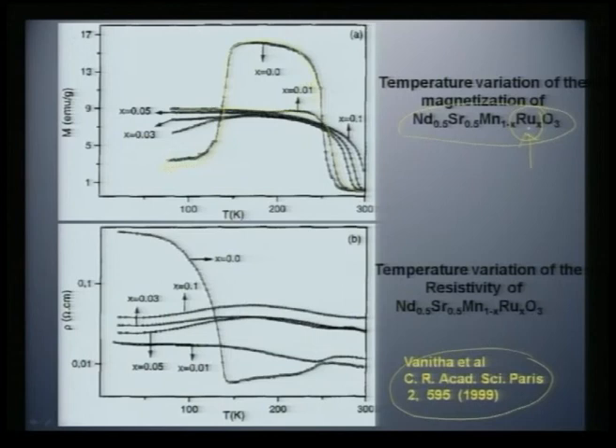And as you substitute more and more of ruthenium, the system becomes more ferromagnetic, and therefore from a charge ordered or an antiferromagnetic state you can make it a ferromagnet by simply substituting with ruthenium. Okay. The same is true when you look at the resistivity versus temperature plot, where you can clearly see that from a charge ordered situation where it is insulating, you can melt this by substituting with ruthenium. Okay. So, from an insulating phase you can go to a metallic phase by substituting ruthenium in the place of manganese, or you can drive the antiferromagnet to a ferromagnet by ruthenium substitution.